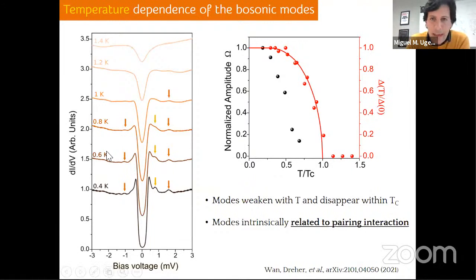So I put these ideas into numbers here. Here you have how the normalized gap behaves as a function of the ratio between the temperature and the critical temperature. It follows a BCS relationship. And this is the amplitude. In black, you see the normalized amplitude for this particular, the most visible mode, which is this one. And you see how it rapidly decays inside the critical temperature.